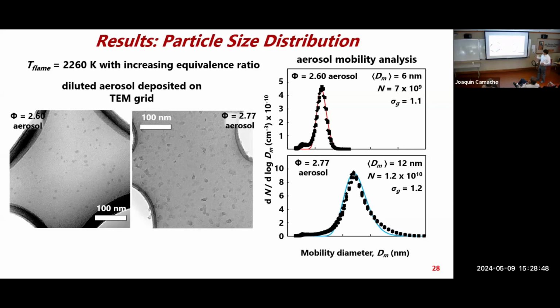And also, here's another type of measurement technique where you probe the flame, dilute the flame, and feed it into this aerosol analyzer. It will classify the sizes by the electrical mobility, and their overall agreement is good. At this equivalence ratio, the median diameter is 6 nanometers. At a higher equivalence ratio, you get bigger particles, and that's corroborated. I didn't put the numbers here. I should have. We counted these, and there's good agreement. But so this is showing that we do indeed have very small nanoparticles, almost molecular scale nanoparticles at the earliest stages of growth, right when they transition from the PAH into a solid particle. We're able to capture them on the film or analyze them from a diluted flow. So these are very small graphene type or very small carbon nanoparticles.